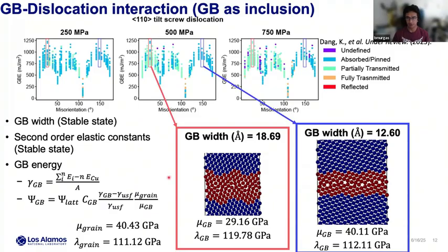So you can see that for the same material, you can have different elastic constants, and that's the two main ingredients of what a defect does: you change your elastic energy and your defect energy. The defect energy is defined in this way, and my elastic energy is defined by changing these elastic constants.